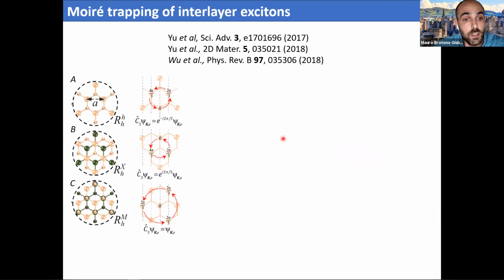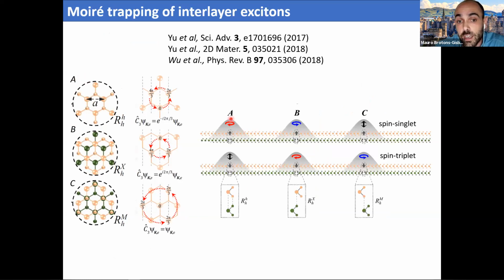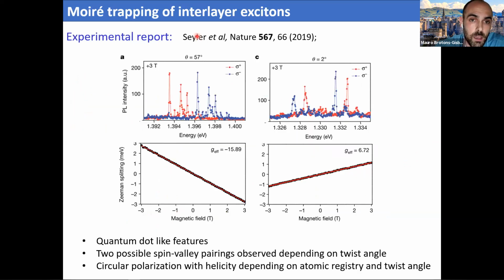On top of that, theory also predicted that depending on the trapping site and the atomic registry, we could have trapped excitons that should show different selection rules depending on whether the exciton has a spin singlet or a spin triplet configuration. It turns out that this was experimentally demonstrated last year by the group of Xiaodong Xu at the University of Washington, where they fabricated heterostructures with stacking angles of close to 60 degrees and close to 0 degrees.